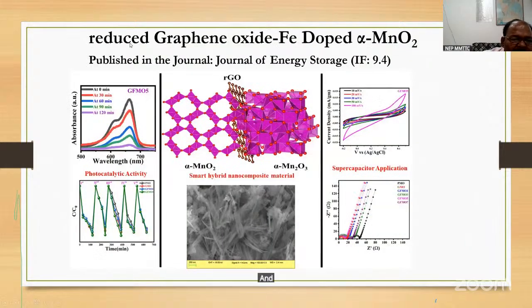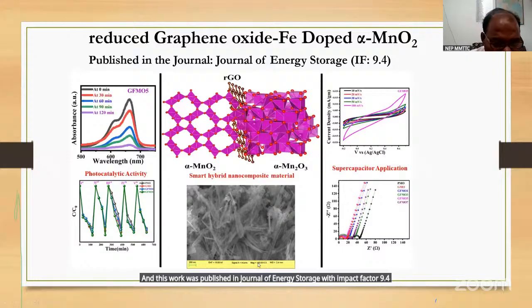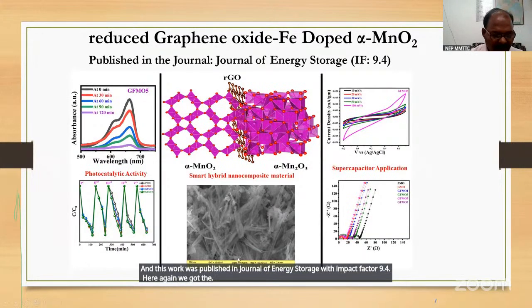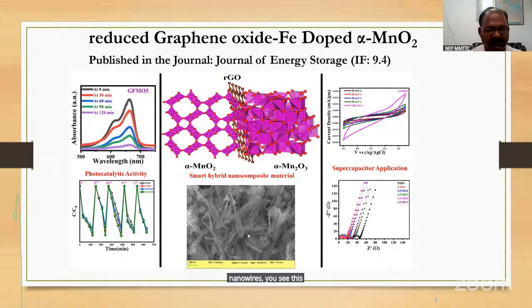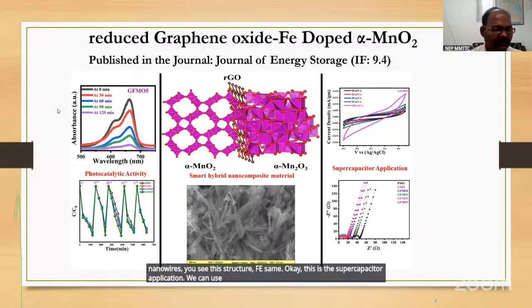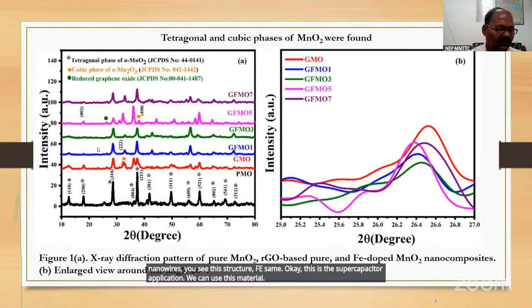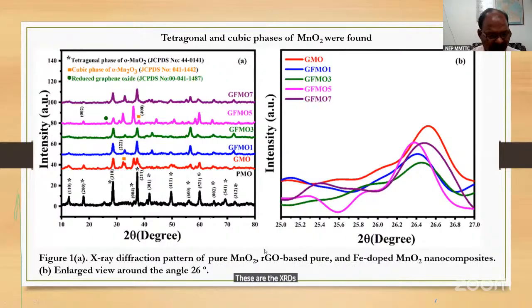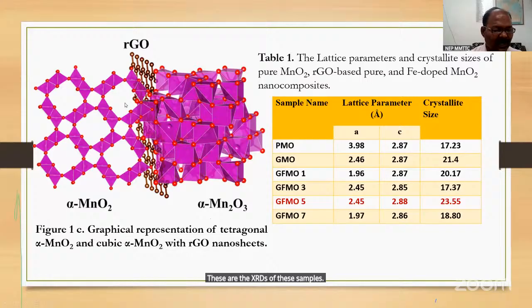And this is the reduced graphene oxide iron-doped alpha MnO2. This work was published in Journal of Energy Storage with impact factor 9.4. Here again, we got the nanowires. You see this structure, the SEM. Okay. This is the supercapacitor application; we can use this material. These are the XRDs of these samples. This is the reduced graphene oxide, and the lattice parameters we calculated, and we got a drastic change in nanocrystallite size.